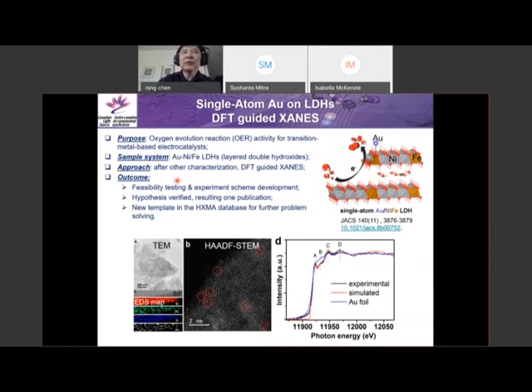The approach the user has used, they have finished all of the other necessary characterization summarized here. All of this characterization provides certain information for the system, but these parts cannot provide the single atom evidence. The only one they can provide is from here, and you can see the brighter single spot here, which suggests there's a single atom gold based on this six-fold rotation axis. But based on this information, we cannot conclusively say this is single atom, and we cannot say which site is occupied.